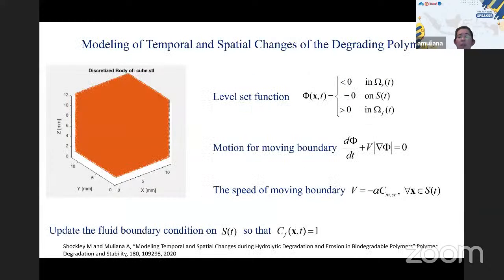Now, how do we model the shape and size change during the degradation? We look at what we call the level set. This is just to tell us where the moving boundary is, where the boundary is now, right? So phi here is the variable that tells us about the body or the geometric component. When it is less than 0, we have a solid polymer. When it is greater than 0, it's all fluid environment. And when it is 0, it is our boundary. So what we are doing is tracking the boundary, and the speed of this boundary change is related to the amount of water-soluble material that exists in the polymer. This is how we track the changes in the size and the geometry during the erosion.